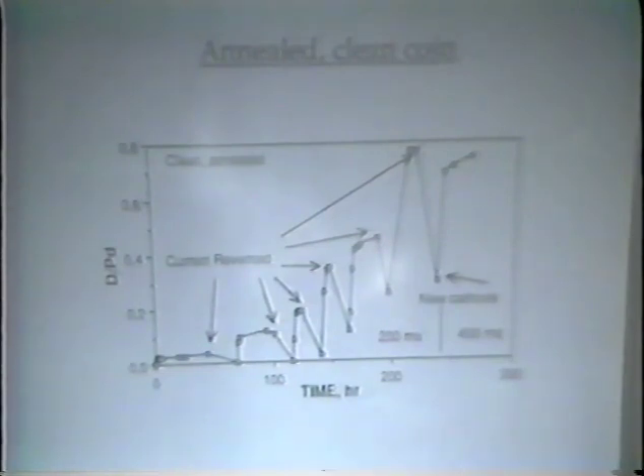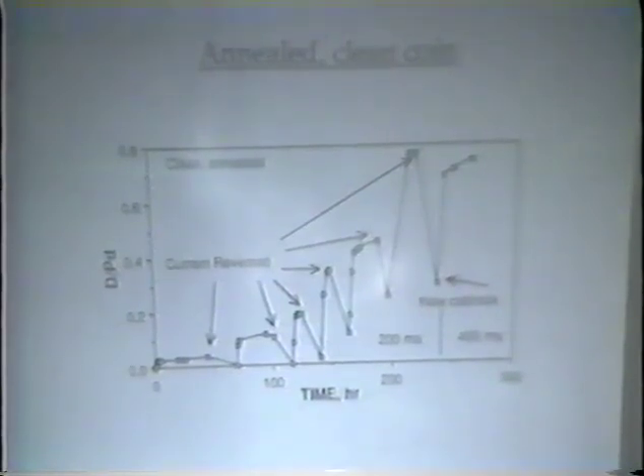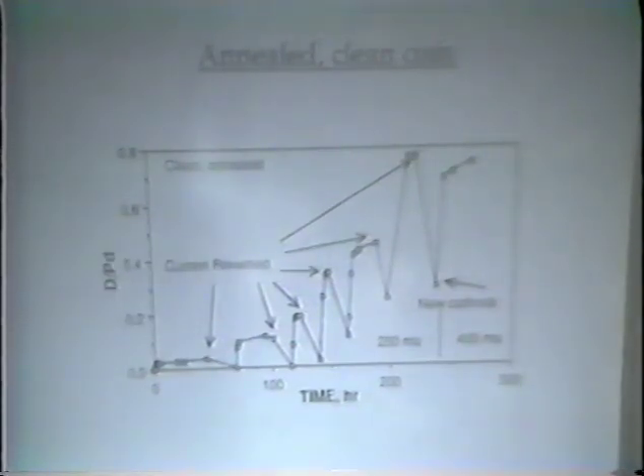We don't know at this point why that happens. It could be because we're introducing dislocations, because as the hydrogen is withdrawn, the lattice does not return to its original condition. It might be because we're removing impurities from the surface that were placed on there during the annealing operation. Or it might be we're applying an impurity to the surface from the cell itself. But this is something that happens in more than one experiment. And you'll see another example. And it does create a little caution because if you're very thorough and you do a good job and you anneal your samples, you might very well never be able to take up deuterium.